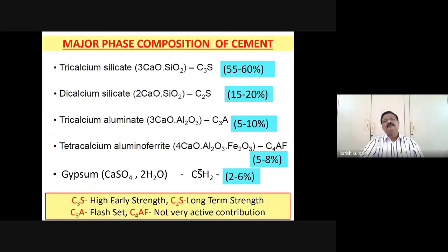So that actually forms the major phases, that is the tricalcium silicate, which is about 60%, which is also called alite, and is mainly responsible for the strength in the concrete. The dicalcium silicate, which is called belite, is responsible for the strength in the concrete, but also good from the durability point of view. The third one is called celite, which is actually tricalcium aluminate. And then the fourth one is called tetracalcium aluminum ferrite.